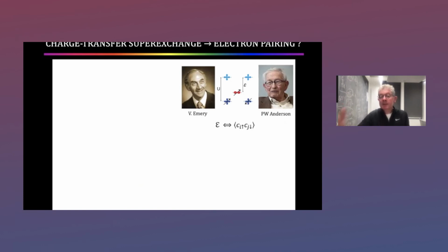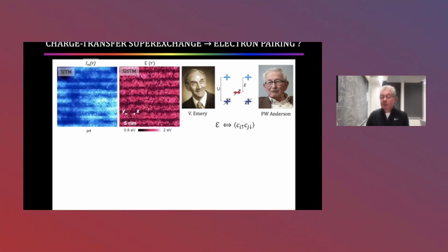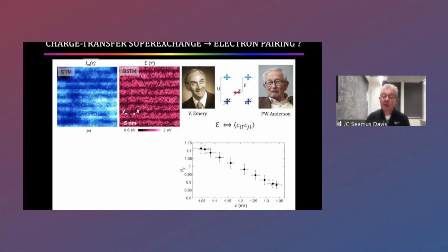The hypothesis is that charge transfer superexchange, charge transfer epsilon, controls the amplitude of the pair wave function. In pursuit of that, we can measure the charge transfer wave function with the charge transfer gap with atomic resolution. We can measure the amplitude of the pair wave function with atomic resolution. And they both modulate by almost 30% in BISCO because Mother Nature is kind to us. That modulation produces this relationship between pair density and charge transfer energy.